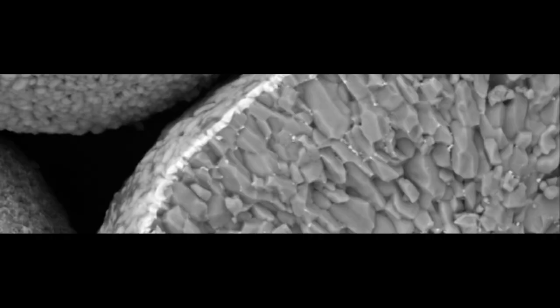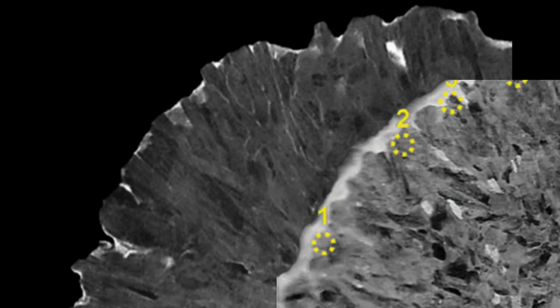The image from Battery Day of Tesla's cathode is roughly in line with what we'd see in a tungsten microstructure cathode or a tungsten heterostructure cathode. There appears to be a protective layer on the surface of the particle. Although the protective layer could be a dedicated coating, that might reduce energy density. Tesla might be able to avoid this energy density loss by going with a hetero or microstructure cathode where a protective coating naturally arises from the doping agent.